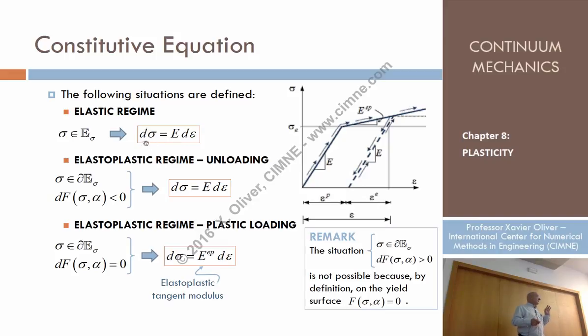So the increment of the stresses and the increment of the strains are related through the Young modulus, as if the material was elastic. What is that? Look, in this diagram, this represents that we are either at one point like that or at one point like that, in the unloading branches, elastic branches. So then incrementally, both increasing the strains or decreasing the strains, there is complete reversibility.